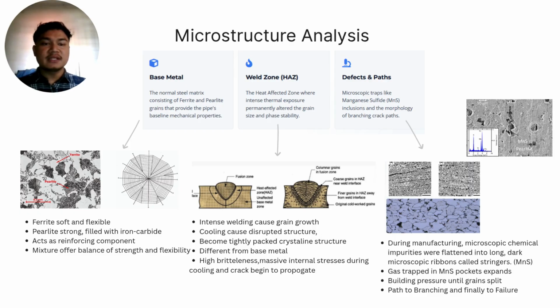Firstly, manganese sulfide stringers. During the manufacturing, microscopic chemical impurities were flattened into long, dark microscopic ribbons called stringers. So it occurs as elongated dark lines under a microscope, and it cuts through healthy grain boundaries and acts as traps for atomic hydrogen absorbed from soil corrosion.